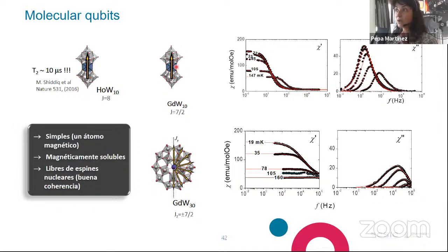In both cases you have one individual gadolinium atom, but what is different is the polyoxometallate cage surrounding it. As you can see here in the susceptibility measurements, the dynamics becomes completely different. This one is much more isotropic, leading to much faster relaxation rates. These measurements allowed us to conclude that this gadolinium tungsten 30 molecule would indeed implement a very interesting quantum bit for quantum computing application.